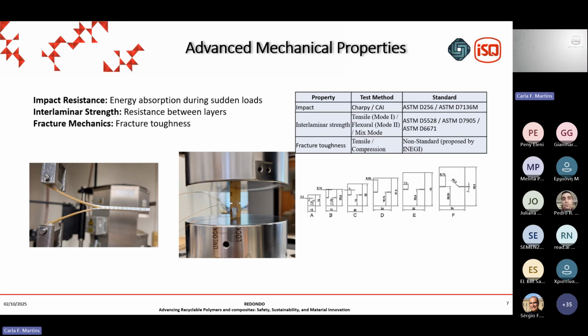So usually it can be done in so-called mode 1 opening, which is depicted there, which is usually by tensile, can be done by flexural, which introduces the so-called mode 2, which is shear, and eventually a mixed mode between 2 of these modes, which require some special rigs. Okay.